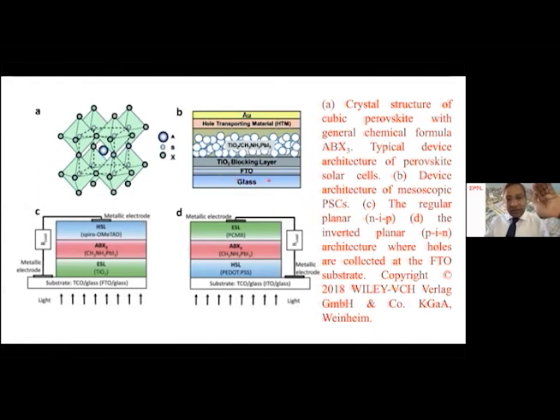So we have a conducting glass, and then we put a blocking layer of TiO2. This is typically deposited by spray coating, followed by TiO2 nanoparticles deposited on top of the blocking layer, infiltrated with perovskite material, then followed by the hole transporting material and gold. So this configuration is called the mesoporous NIP configuration.